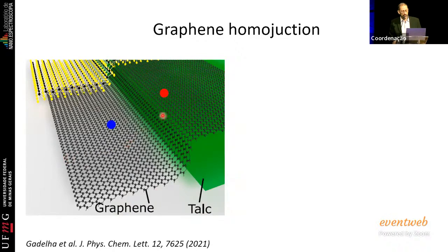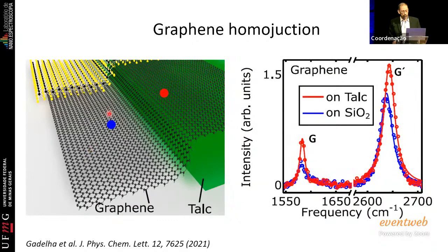If you take graphene and you place graphene on a substrate like glass, it will get P-doped. But if you put talc, that is another two-dimensional material, on one piece of graphene, the talc dopes P much more strongly than the glass, okay? So this is doped and this is doped, but this is much more highly P-doped than this region here, okay? And if you measure the spectrum here and you measure the spectrum there, you see the blue and the red here, that the peaks change. They change in frequency, they change in intensity. And it is understanding these changes, made initially by these Korean groups, that gives you information about doping.